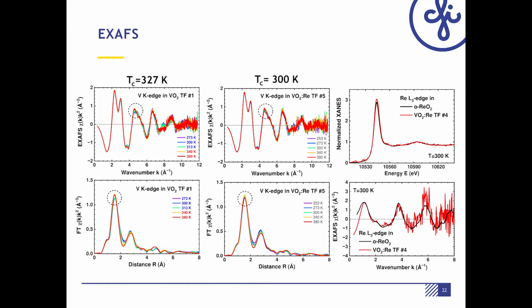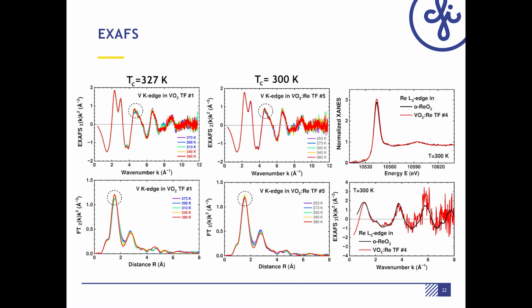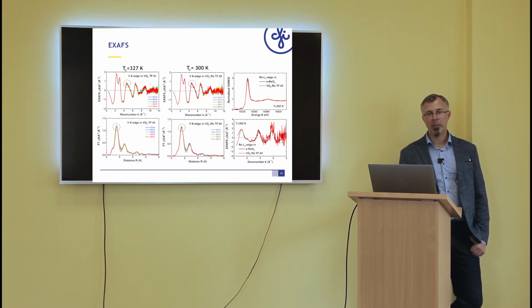What we can see and what we can conclude. Actually, EXAFS is a rare method which allows to study local surrounding of doping elements like rhenium in this case. We analyzed the spectrum of rhenium which is in matrix of crystalline vanadium dioxide. And spectrum coincided with orthorhombic ReO2. And that means that rhenium indeed substituted vanadium and effectively works as a dopant.